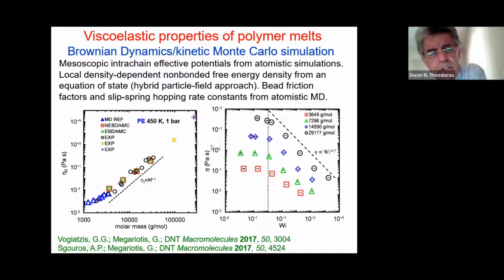On the right-hand side, we see the viscosity as a function of the shear rate imposed on a melt under conditions of steady shear flow. Essentially, we have used Lees-Edwards boundary conditions with exactly the same mesoscopic simulation that we described, and we are able to look at viscosity essentially as the ratio of the shear divided by the shear rate, gamma dot. And instead of the shear rate, we use a dimensionless quantity here, the Weissenberg number, which is the shear rate multiplied by the longest relaxation time of the melt. What we observe is that at the low Weissenberg numbers, when, in other words, the flow is slow, it is gentle, the shear viscosity assumes a plateau value. This is the so-called Newtonian plateau. And it's exactly this plateau value that we were plotting in the left-hand side plot.